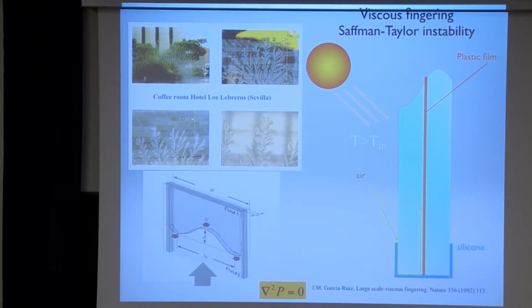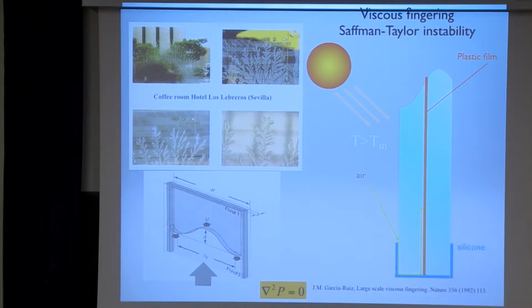So there were windows, okay, windows with two glasses, and here is a plastic film. This is an anti-crack window. This is how the anti-crack window looks like. Okay, so you have the two glasses and then a plastic film. You can have maybe three glasses, yeah, but these are only two. So what happened is that when they made the window in Sevilla, it was not very well sealed here in the lower part.